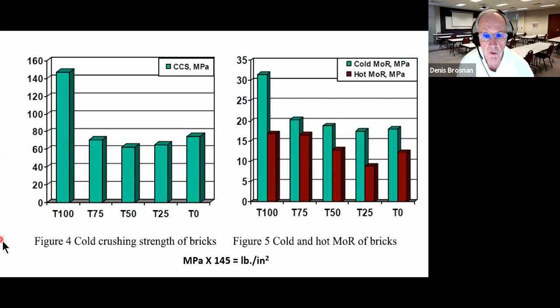The authors report the highest cold crushing strengths for the tabular alumina mixes in excess of 140 megapascals. And if you multiply 140 by 145, you'll get that in pounds per square inch. Interestingly, they compared the cold modulus of rupture to the hot modulus of rupture.